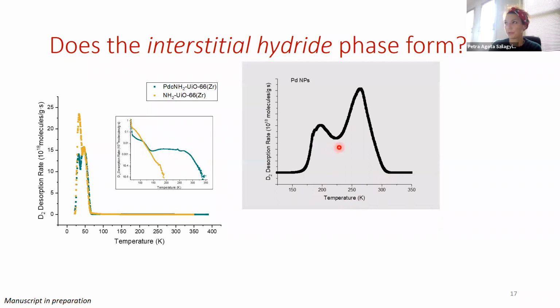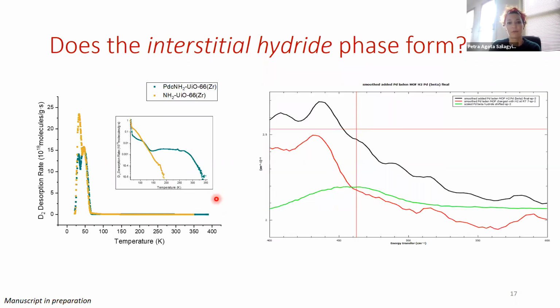And just to show you, if we have chemisorption from palladium nanoparticles, it has actually a very characteristic shape, with two different peaks corresponding to desorption from the alpha and beta phases. And as you can see, this is completely absent in here. We just have a big smudge, which already gave us confidence that the beta phase has not formed here. But we also carried out some inelastic neutron scattering.